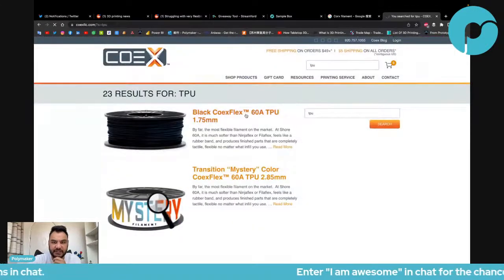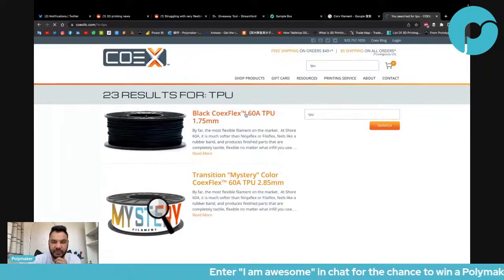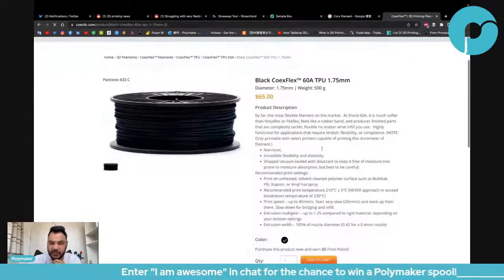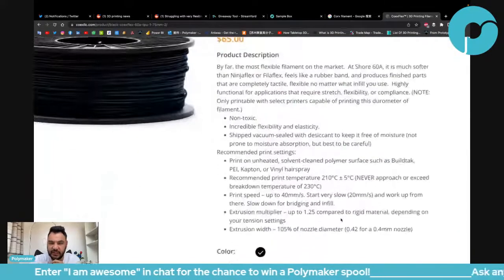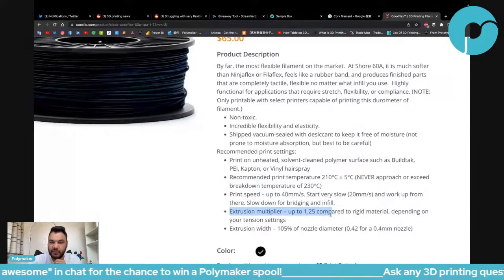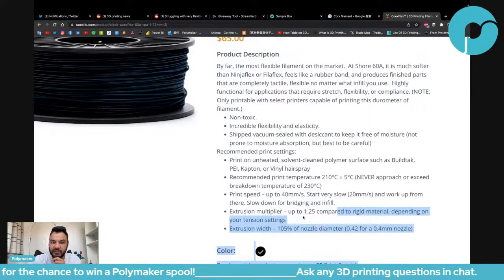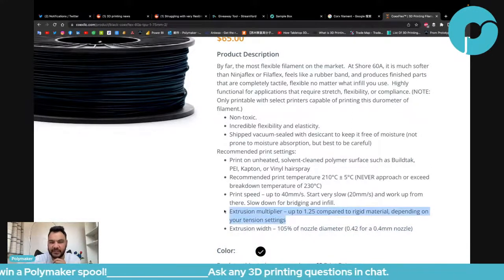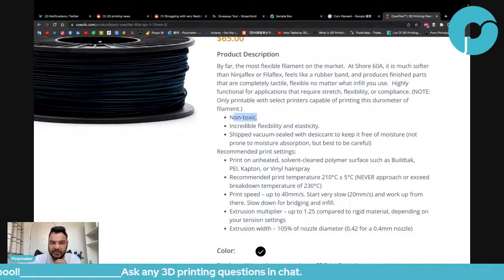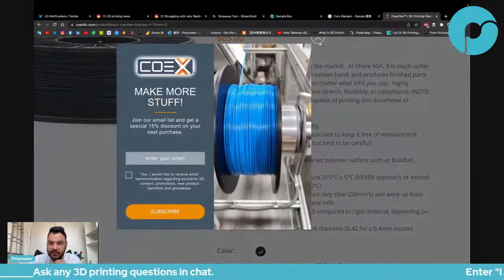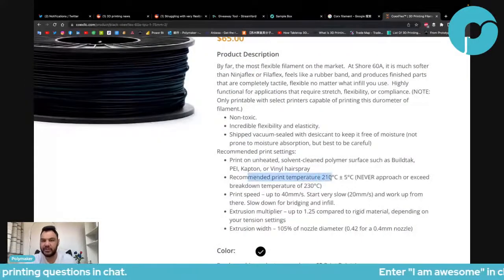Coex Flex 60A TPU. Okay. What's their printing setting? Extrusion multiplier up to 1.25 compared to rigid material, depending on your tension setting. Oh, I like that. Non-toxic, and so on. Recommended print temperature: 210 plus or minus 5, never approach or exceed breakdown temperature.